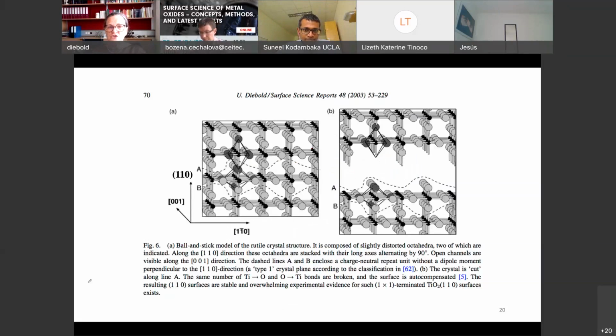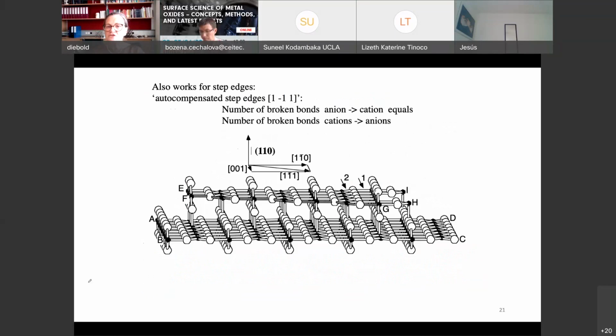So actually, this is how this surface looks. The surface has these leftover titanium atoms that miss 1 partner. They are 6-fold octahedral in the bulk, now they are 5-fold coordinated. This oxygen actually had 3 partners in the bulk. Missing 1, the oxygen atoms are 2-fold coordinated, and these we call the so-called bridging oxygen atoms. So it's really powerful, actually.